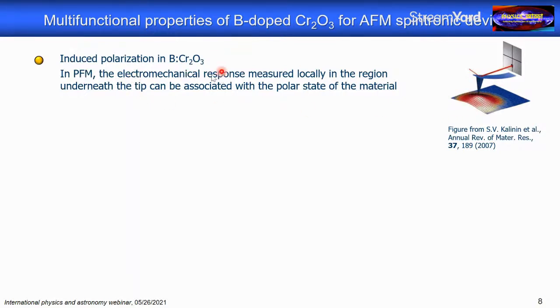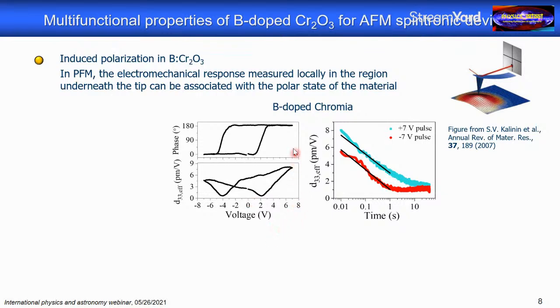So that's what we did with these materials, and to our surprise, we found results that very much looked like a ferroelectric material. So you see here this hysteresis loop in the phase signal of this atomic force microscope. And you see this butterfly-shaped curve, which is also characteristic for ferroelectrics, in the effective piezoelectric coefficient D33 as a function of applied voltage. So this almost looks as if the material became ferroelectric, but it's important to stress